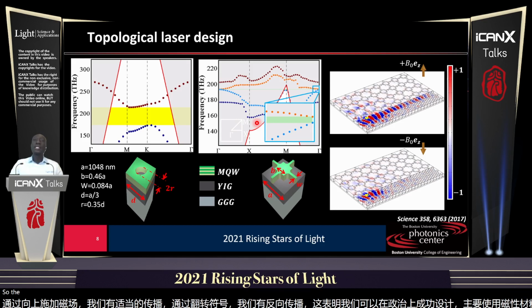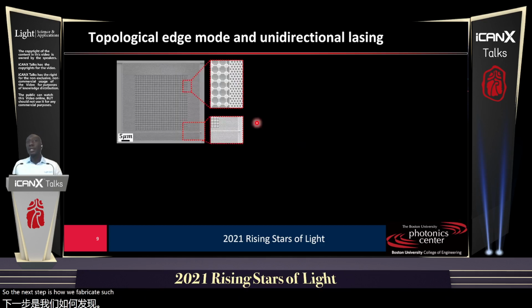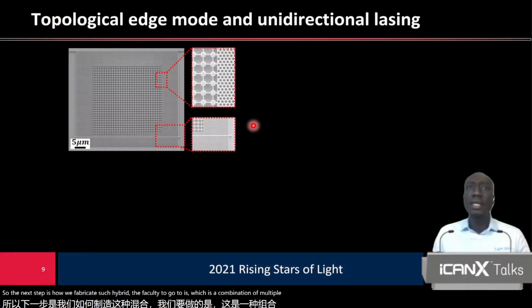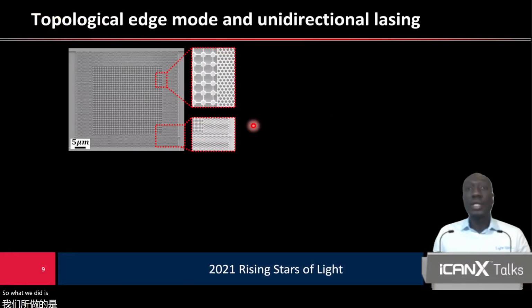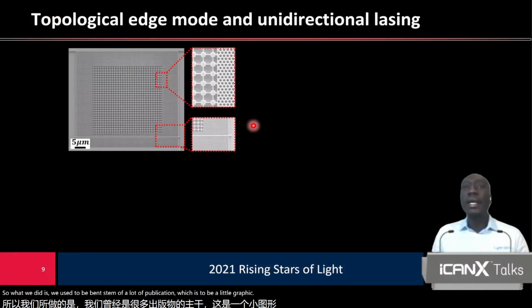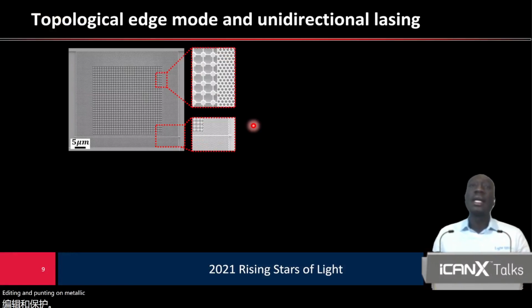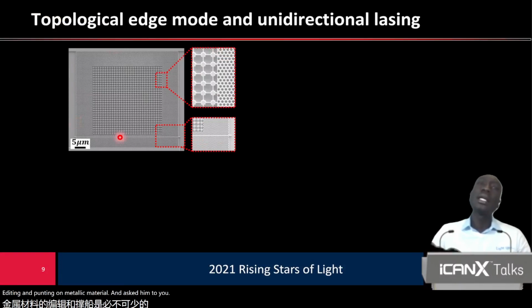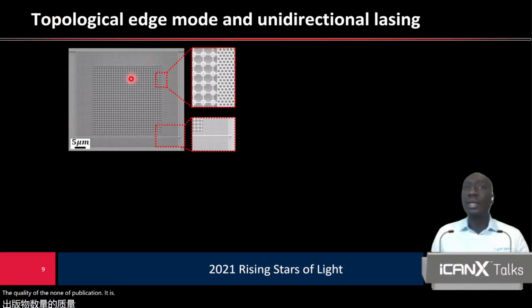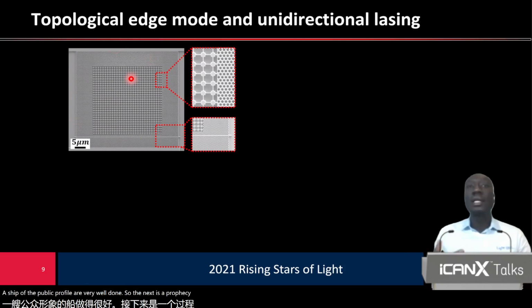So the next step is how we fabricate such a hybrid structure, which is a combination of multiple materials. We used three main steps of nanofabrication: e-beam lithography, etching, and bonding on magnetic material. As seen here, the quality of the nanofabrication is very well done, and the shape of the photonic crystal is very well done.